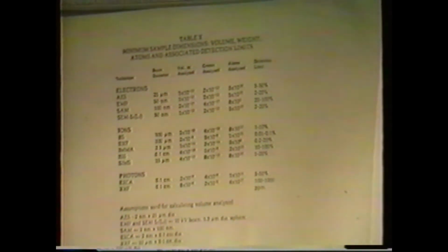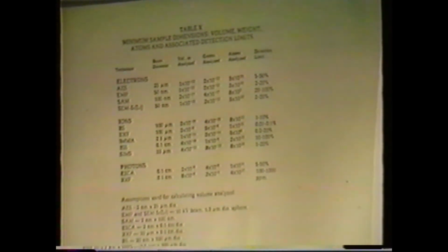In terms of what's the level in the layer, as we discussed the other day, it's a few tenths of a percent. So if you have an impurity in the top layer that's not yttrium, barium, copper, and oxygen, if it's less than a tenth of a percent, then you won't see it. In terms of absolute sensitivity, it's quite sensitive, but of course the whole signal is coming from that top surface region. Well, what levels of impurity cause problems?